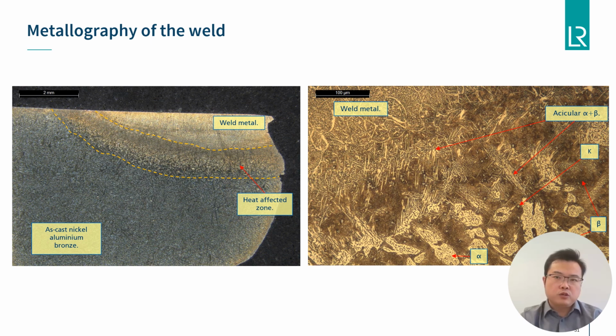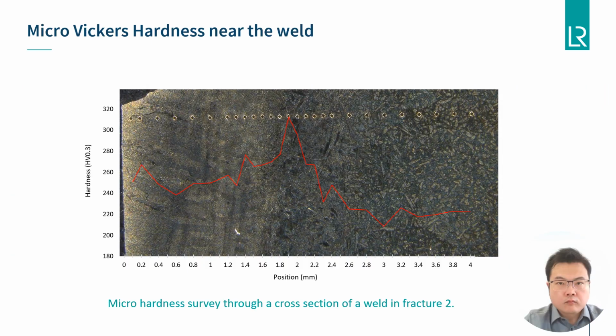The weld metal is fused into the cast material and the heat from the process diffused into the nickel aluminium bronze, forming the heat-affected zone. The acicular alpha and beta phase in the weld metal and specifically in the heat-affected zone is definitely very undesirable because of its morphology. Obviously, the welding of the nickel aluminium bronze blade had a significant effect on the microstructure.